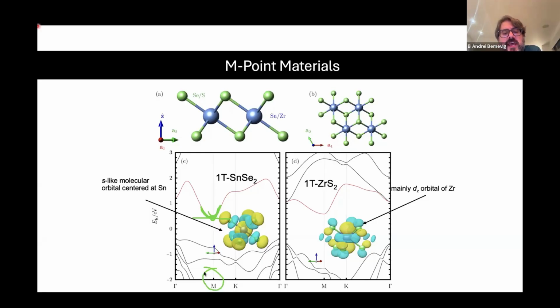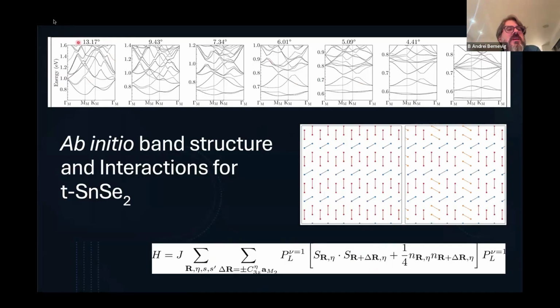Also notice that this twisting is that of a completely different point than in graphene. This is the endpoint. In graphene and in MoTe2, we are twisting the K point. The difference between these crystallographic points might not mean much in principle, but is actually dramatic because the symmetries and the different Hamiltonians act differently. So indeed, if we twist these, this calculation takes about 6 months to do. You can clearly see that at small angle, a flat band emerges. In this flat band, interactions will take over, and if you compute the influence of the interactions, you will get the Hamiltonian of a t-J model, a one-dimensional t-J model, 3 of them because of the endpoint. So this model, to make a long story short, acts as a simulator for a quantum spin liquid.